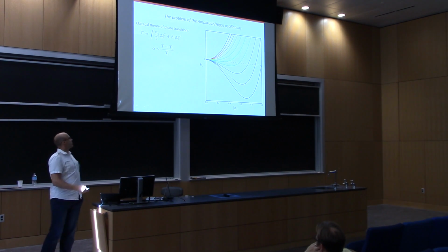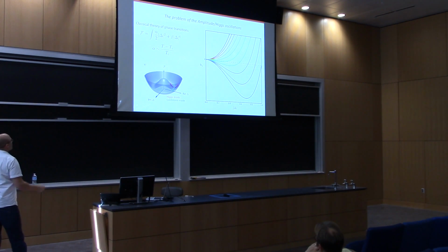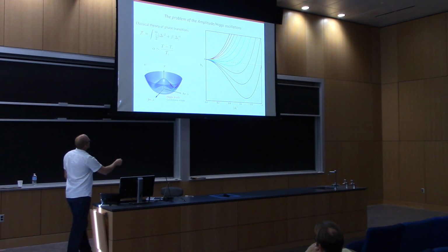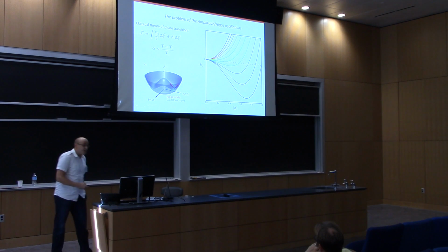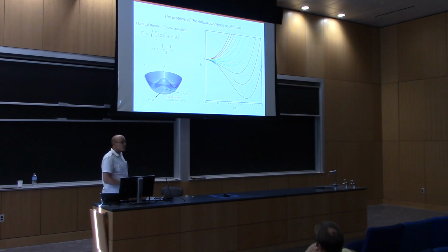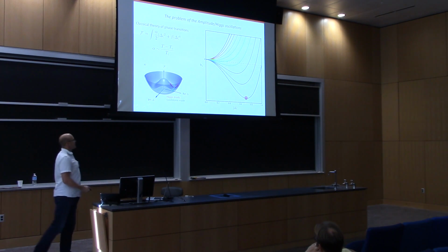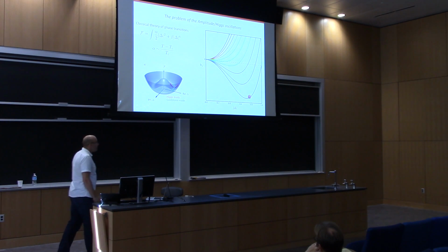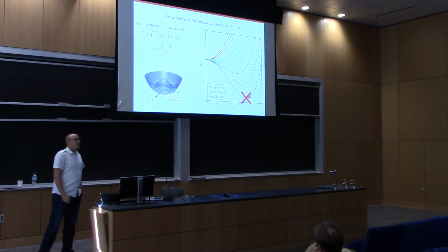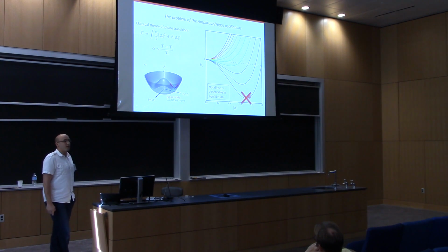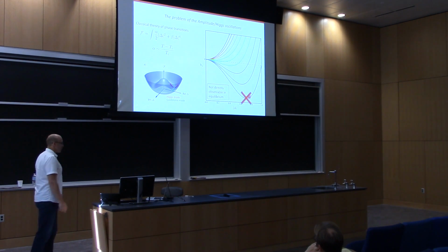This is a superconductor, so this is a two-dimensional order. And in principle, I should have oscillations this way, which correspond to this side, and then some kind of free phase oscillation, which in the presence of electron-electron interactions gets gapped out. So an amplitude mode would be something that's down there, and I can somehow perturb the system, and it sort of wiggles back and forth. The problem is, in equilibrium, this does not happen, because the superconducting order does not couple in linear order. It doesn't couple to light, it doesn't couple to all sorts of fields in linear order.